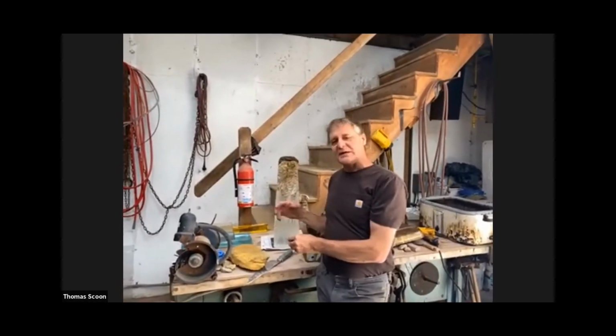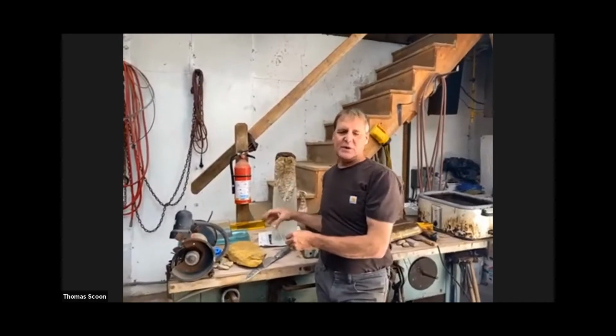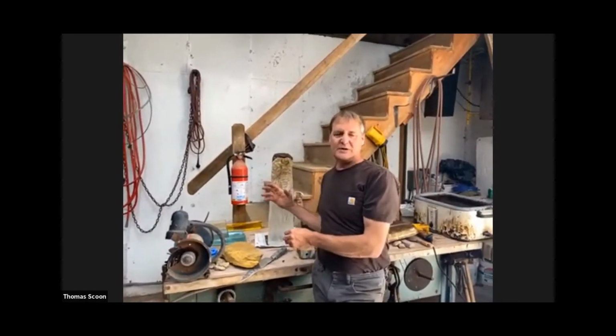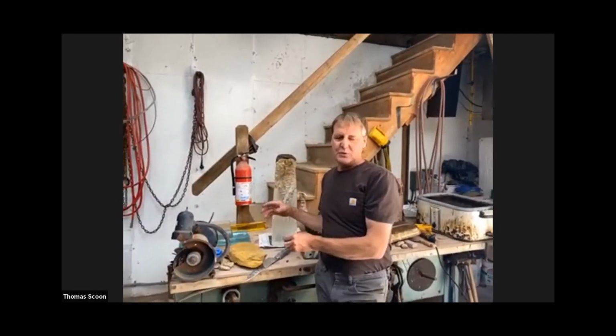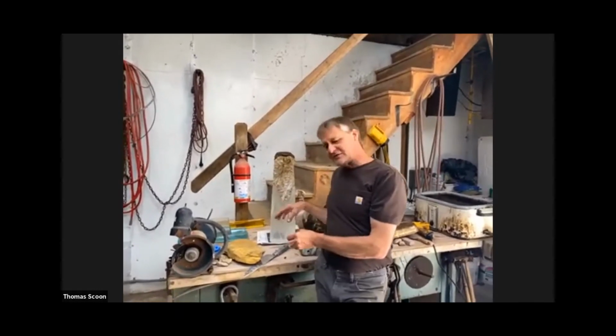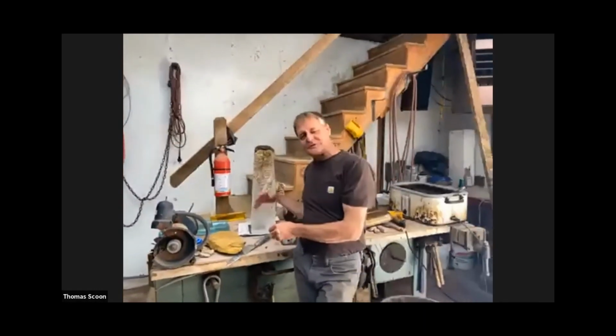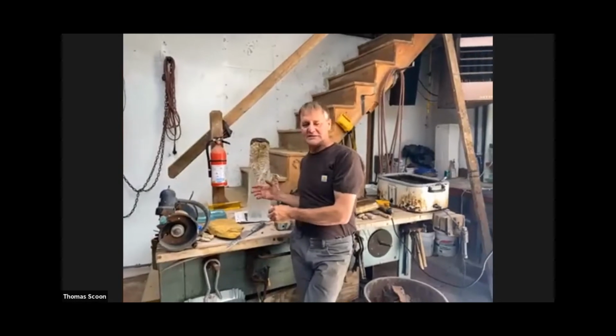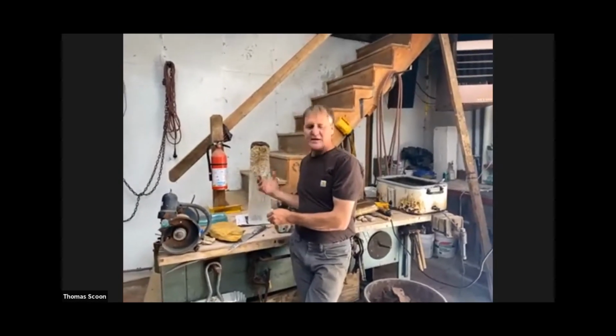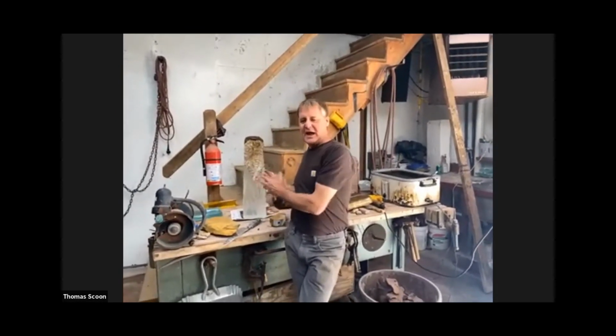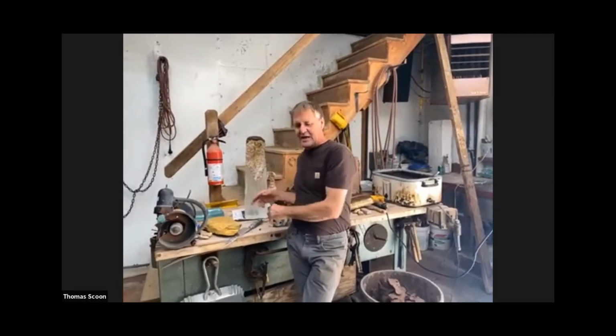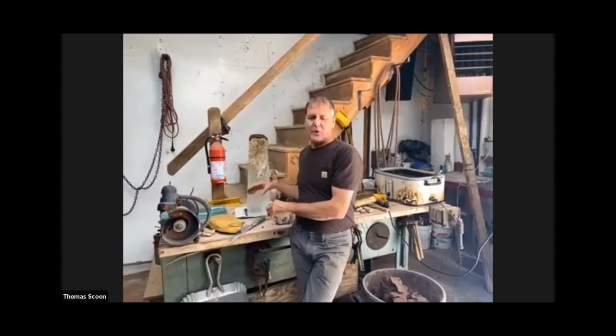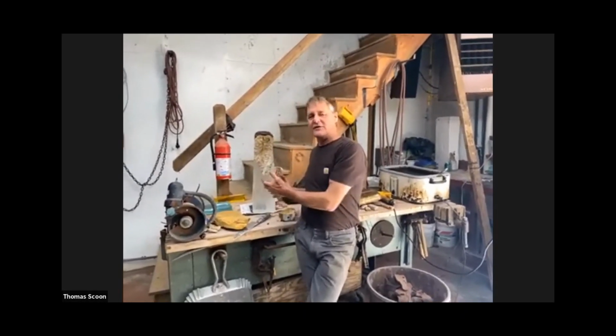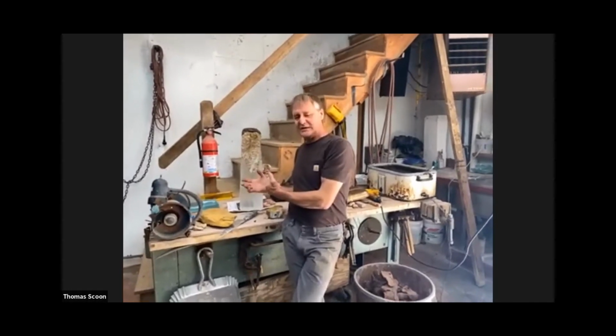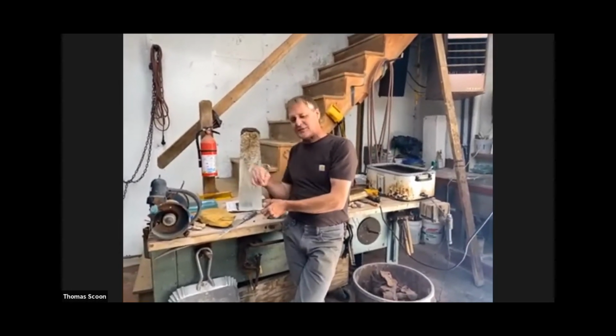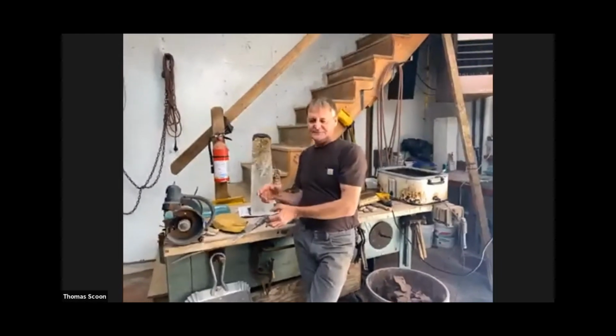Put the mold in the kiln. It takes a day, 24 hours, to dry the mold out and come up to 1,000. At that point, it takes like 5 or 6 hours for the kiln to come from 1,000 to 1,650 to get ready to put the glass in. And then it takes 5 or 6 hours to add that glass to fill the mold up. Then this would be in the kiln for probably about 150 hours after that, slowly annealing. The most crucial time is from 1,000 to 700 degrees.